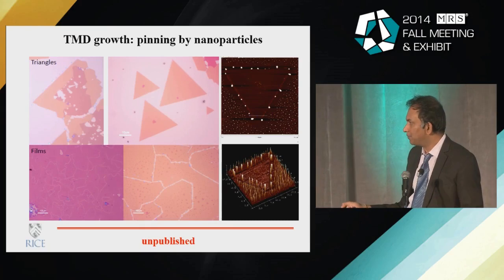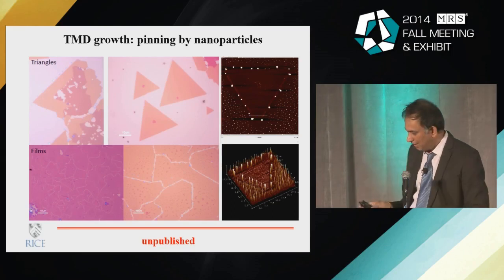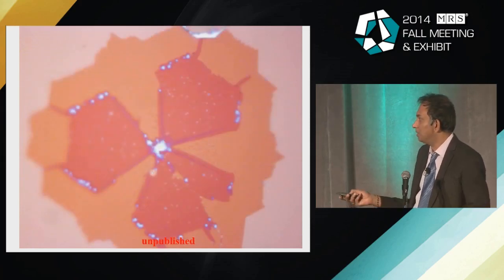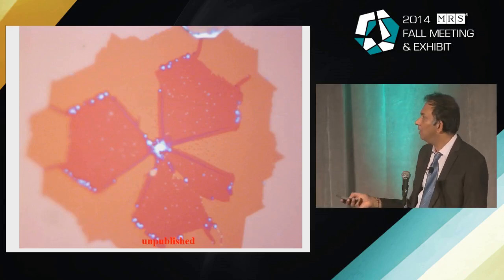I mean, there are gaps. These are not really grain boundaries. These are basically gaps because the structures have actually stopped growing at some point. This has to do perhaps with this pinning that I mentioned, where these particles, which also seem to be molybdenum sulfide but not really this 2D structure, pin the growth around the boundaries, and then they stop growing. So there's a bilayer system.